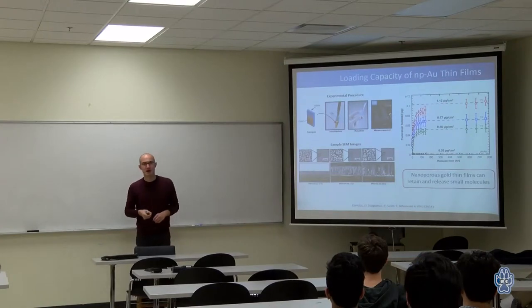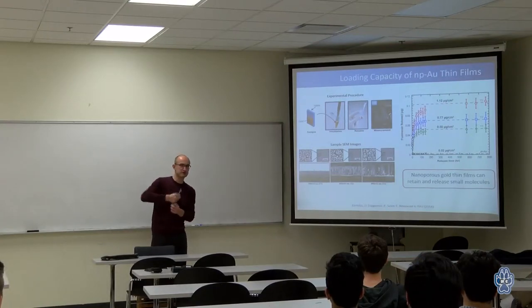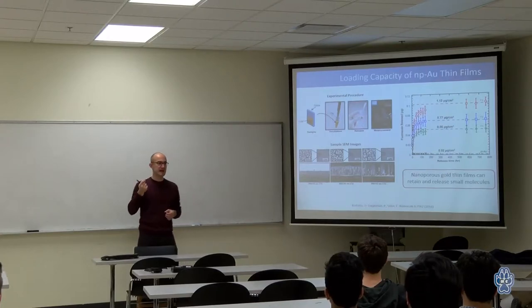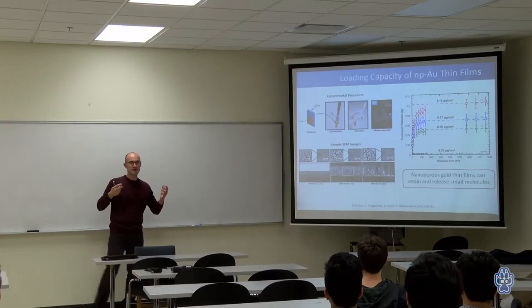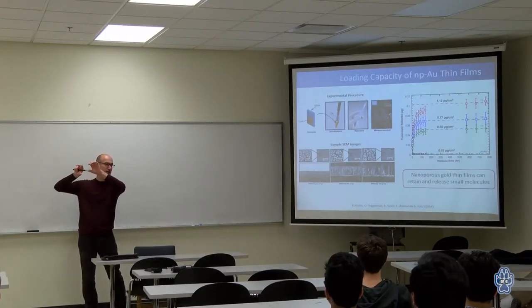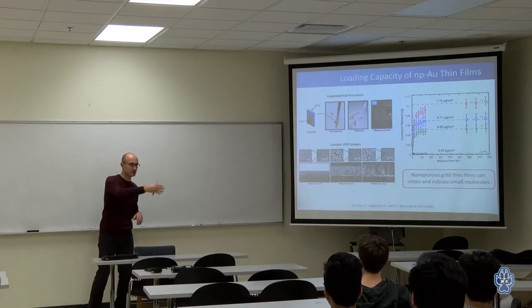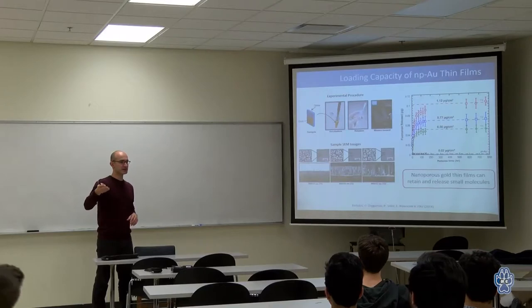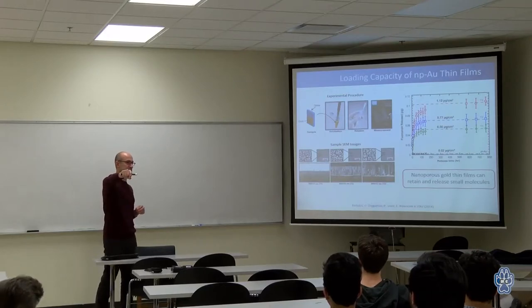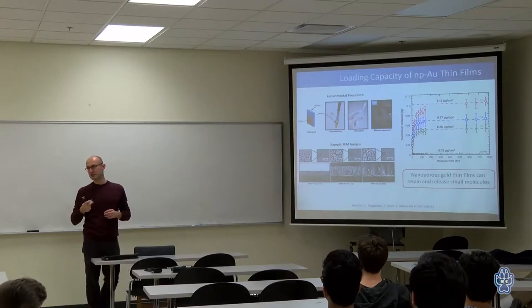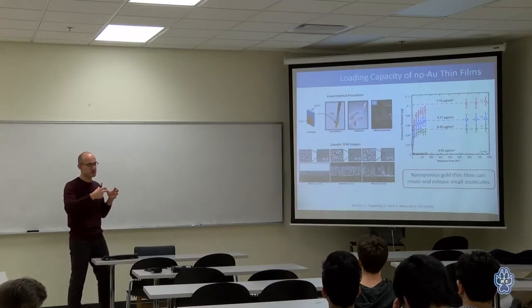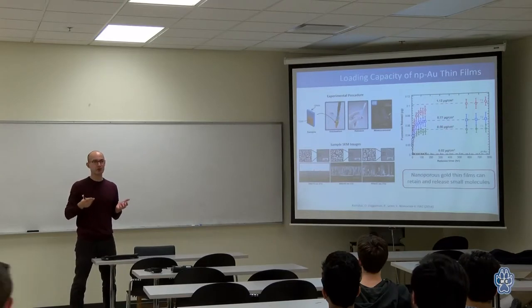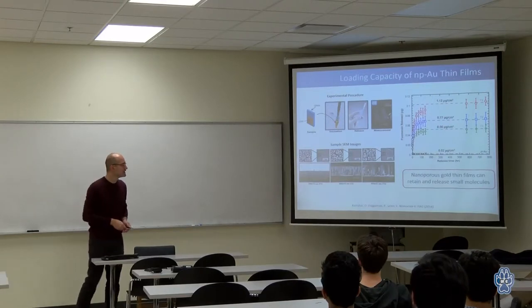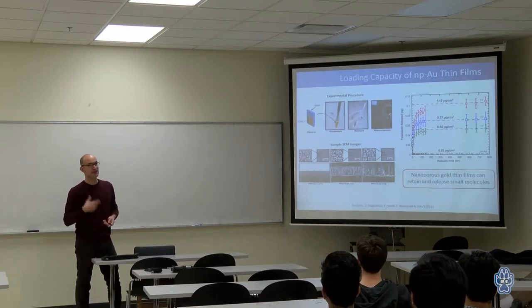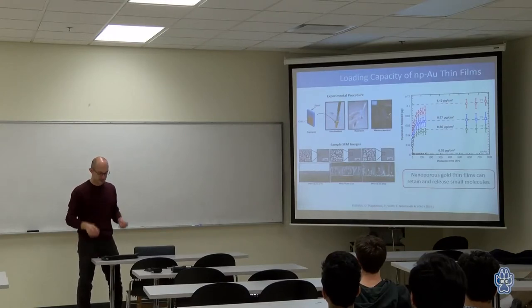What happens is, you can think of this porous structure as a continuous channel. But now these are so small that the drug molecules are a similar size as the channel. So imagine you are running through a very narrow tunnel and it's dark, so you are bouncing off the walls. How much you interact with the wall determines how fast you would leave the tunnel. It's the same idea here. What determines how fast a drug molecule leaves this porous sponge is how many times and how long it interacts with the surfaces as it's coming out. So this gives us a lot of opportunities to tune how fast you can get the drug molecules out.